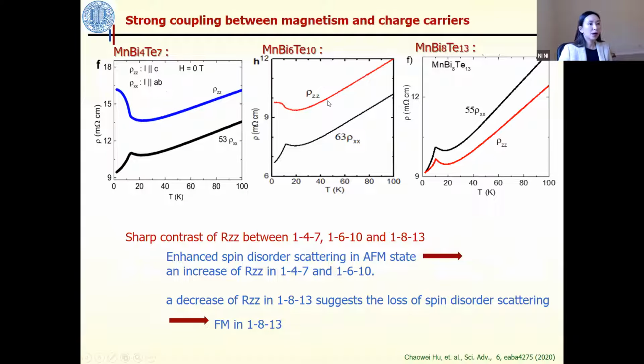There is actually strong coupling between magnetism and charge carriers. If you look at the band structure, the manganese bands are way below or above the Fermi level, and at the Fermi level it is mainly the bismuth and tellurium bands. However, even for that, we saw strong coupling between the magnetism and the charge carriers.